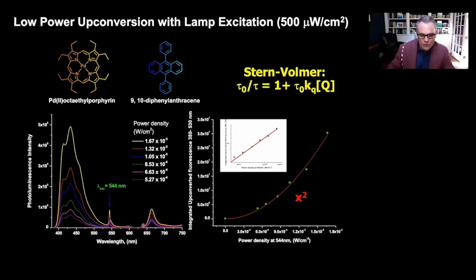And you can see the residual porphyrin phosphorescence is here, but look at the sensitized DPA fluorescence. And you notice exactly what I was telling you. It's not inner filtered anymore. That's the authentic fluorescence spectrum of diphenylanthracene. And it still follows the quadratic dependence as expected.